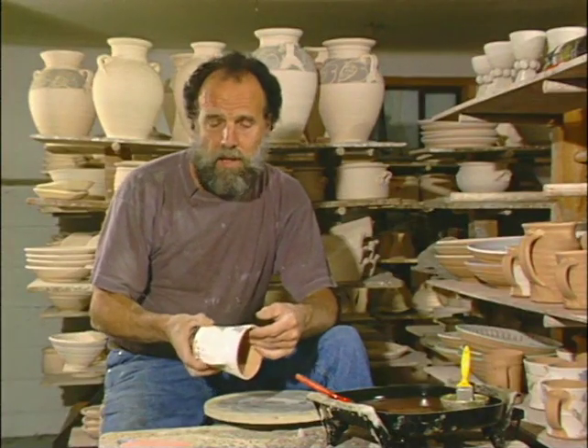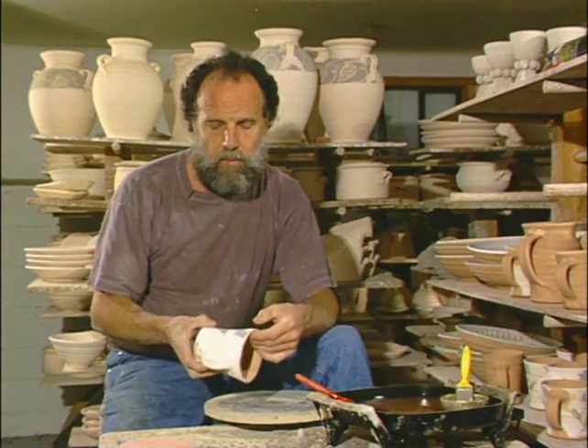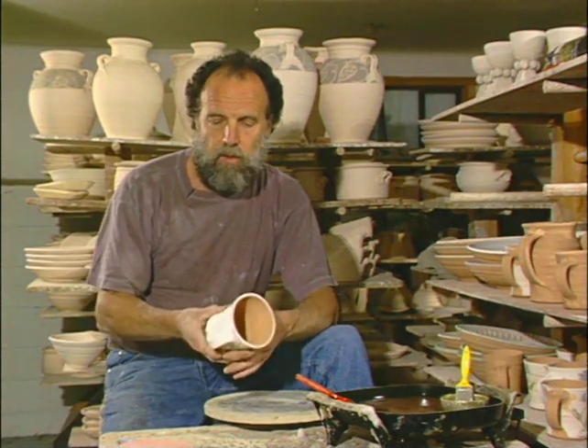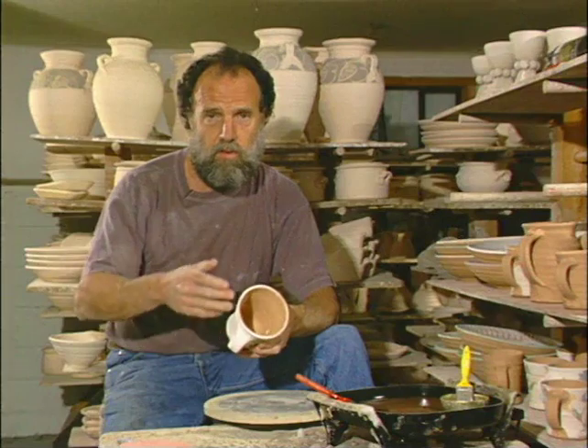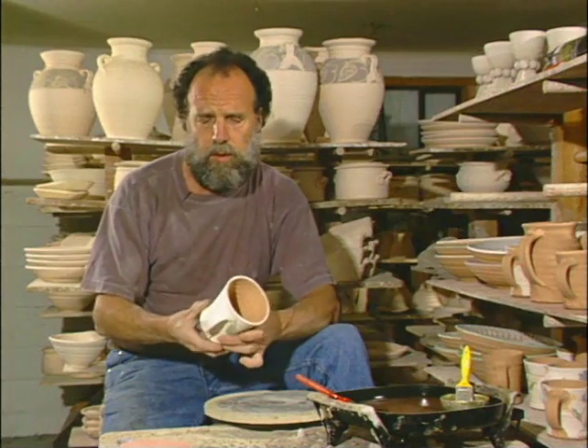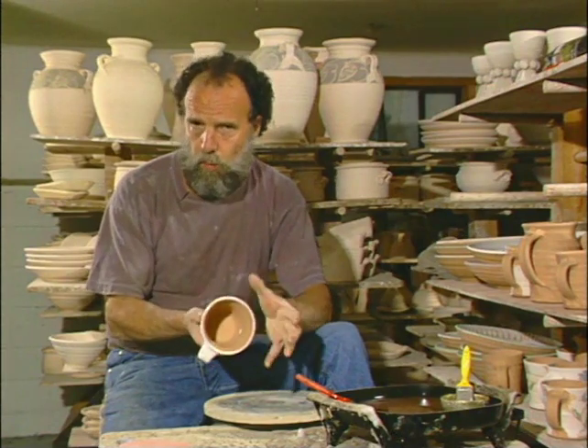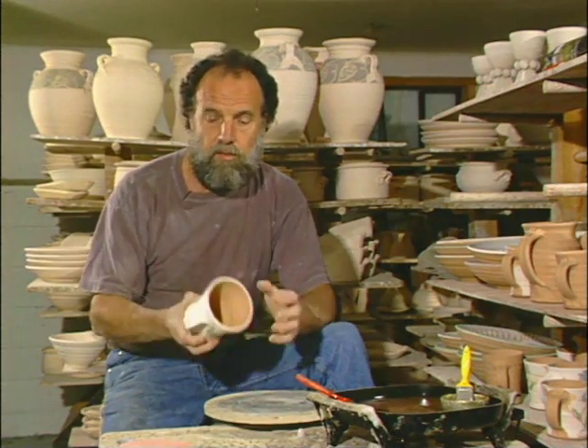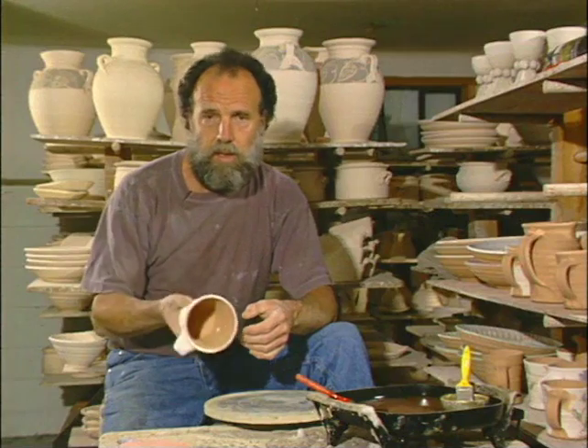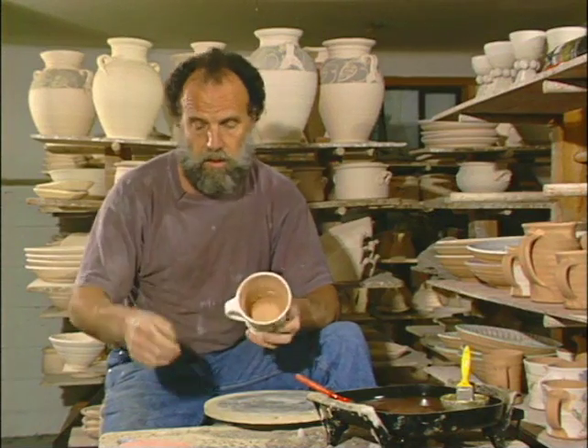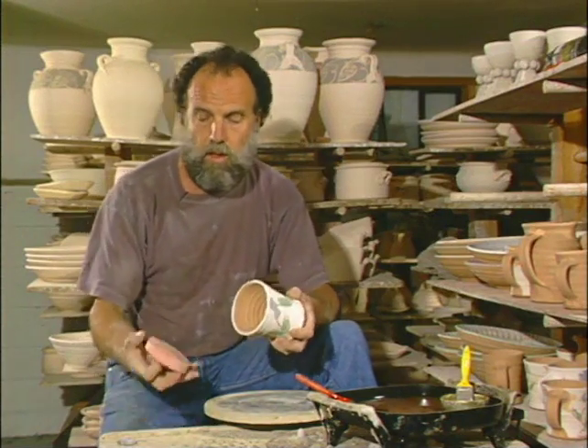We're about to glaze these pots, so before we do, there's a couple of things that we need to do in preparation. The first is to check that there's no dust on the pots. The best way to ensure that is to see that the pots don't get dusty while you're storing them. The reason for not having dust on it is that the glaze may well crawl away from the dusty spots. So if you find you've got dusty spots, you can take them outside and blow them off. You don't want that dust in the room with you, so blow it off outside.